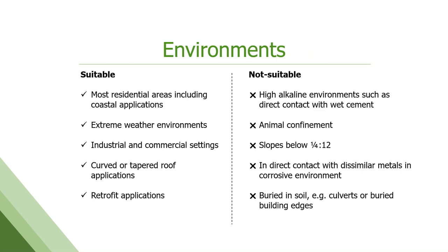We do need to talk about suitable and unsuitable environments for the Galvalume product. There are a few areas where it really shouldn't be used, and that's high alkaline environments. The high alkaline will attack the aluminum component. So animal confinement and direct contact with wet cement are problematic. Low slopes without proper water drainage cause corrosion, but that sort of applies to all metal roof products. Dissimilar metals in a corrosive environment can be problematic, and we actually have several slides on that later on, so we'll dig into that a little bit deeper. And then buried in soil, the zinc aluminum product doesn't do well in soil. It really degrades quite quickly, so you want to stick to galvanized for those kinds of applications.